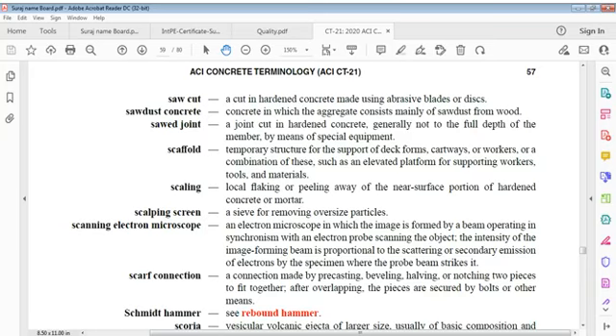Sawdust concrete, I can say, is a simplified term. Let us say it finds in this study sawdust concrete has been produced where river sand is replaced with sawdust by 5%, 10% and 15% of total sand volume. Result shows that most optimum design for producing sawdust concrete is that with 10% replacement of river sand, based on compressive strength of this.